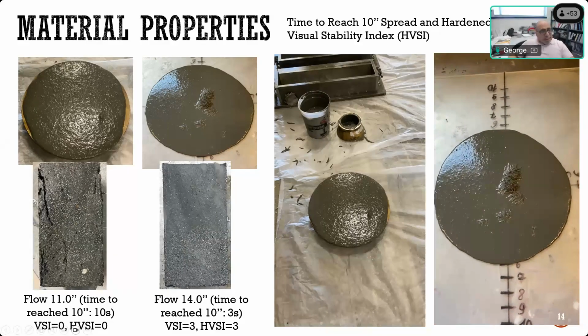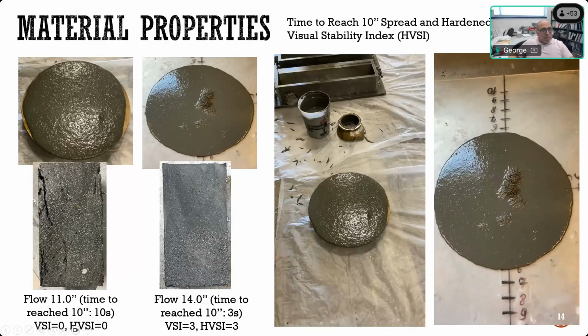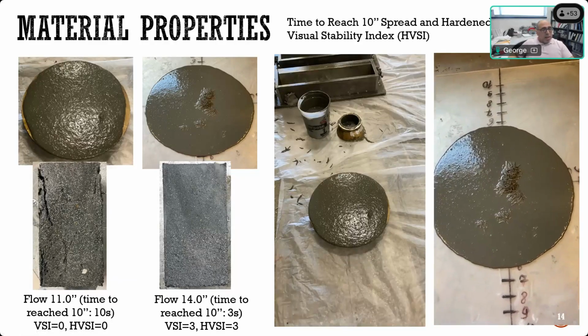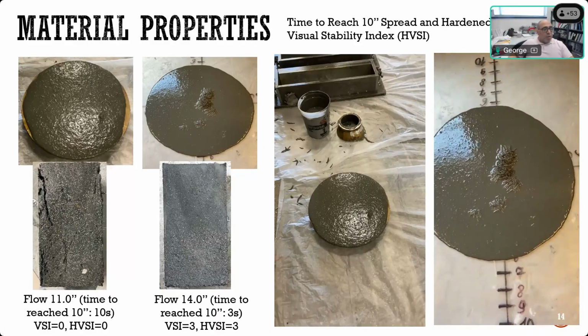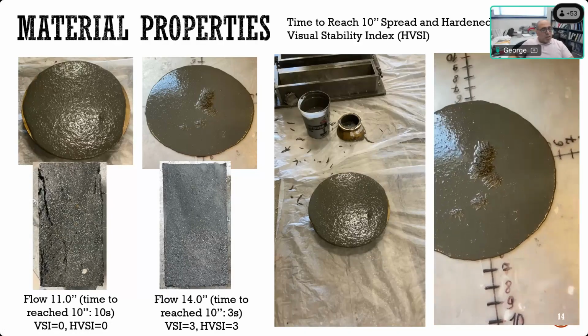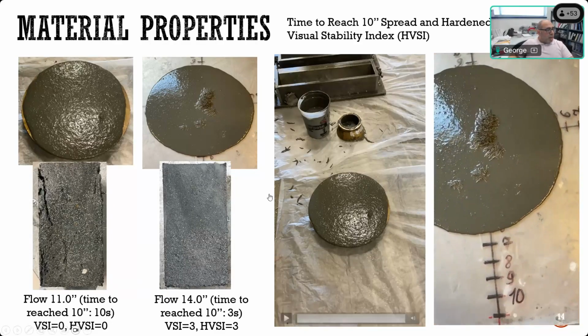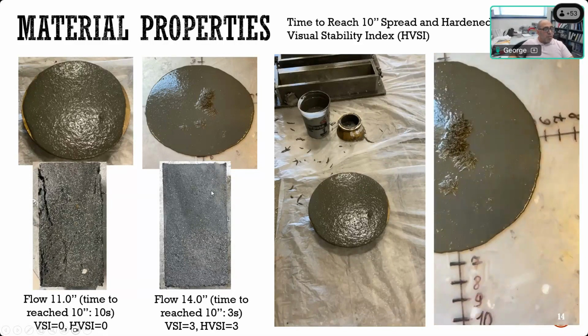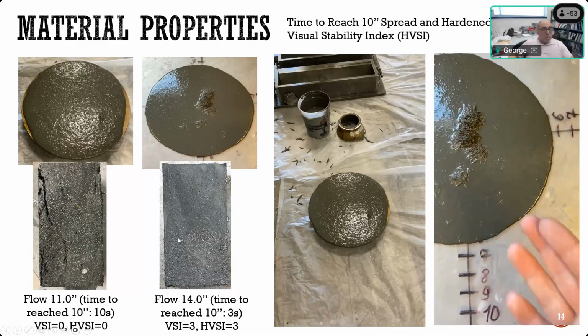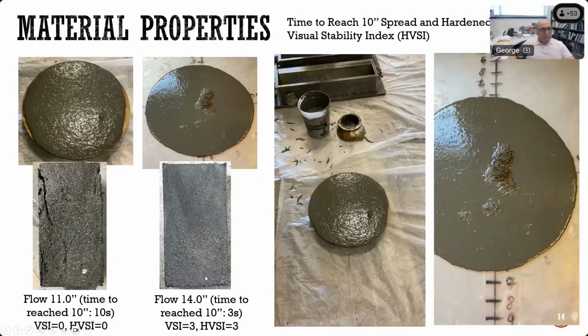You can also detect that later if you make cylinders and slice them. You can see this is a stable mix on the left side, where all the fibers are distributed equally from top and bottom. But the one next to it on the right has a very big part of the top that doesn't have any fibers, and all the fibers are pretty much at the bottom. This is not acceptable in this case.